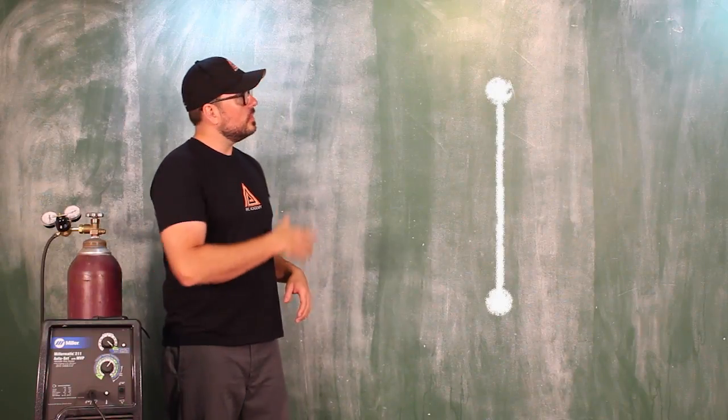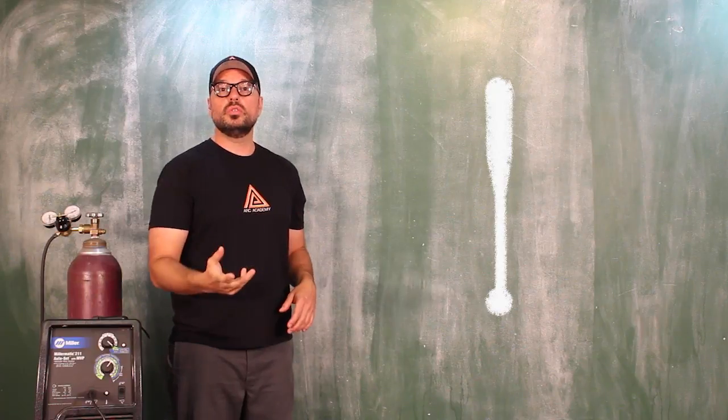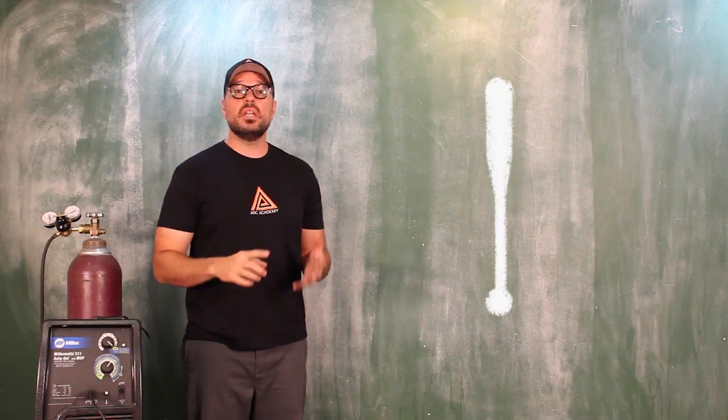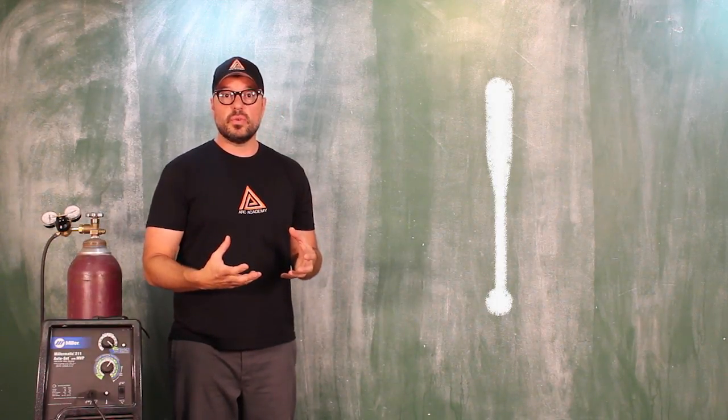Now here's what's going to happen: if you start off, you're going pretty good, and then you jerk through the motion or you go too fast, the edges are going to pull in—they're going to suck in on you. You're not applying enough heat or enough filler metal to create the proper size bead for the thickness of the material.